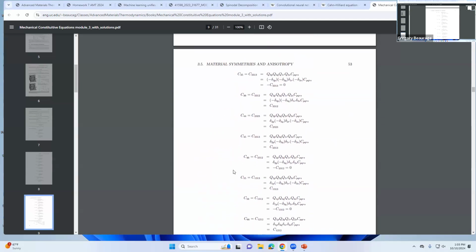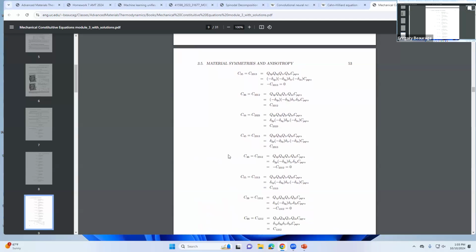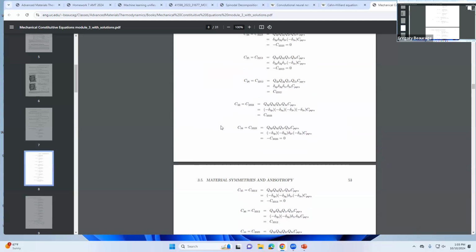Normally, except if you pull something like a polymer, like if you extrude a polymer through a die, it swells laterally. It's called a normal stress. And the harder you shear it, the bigger it swells. So that's called the normal stress coefficient. So that would be one of these weird C numbers. I don't know which one, right? But there are times when engineers use different combinations of these.